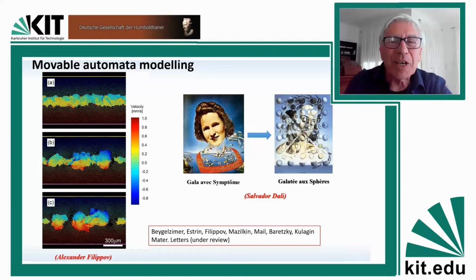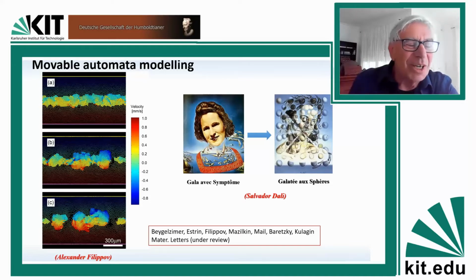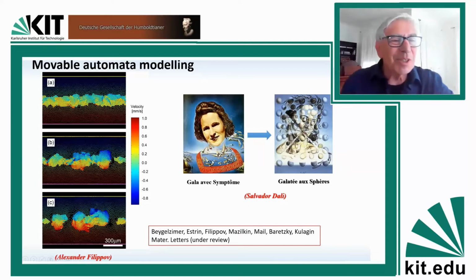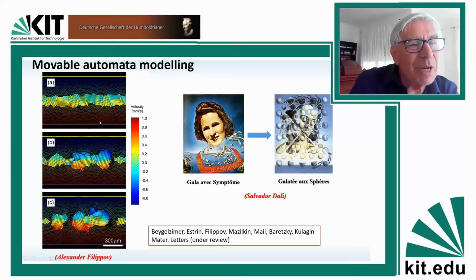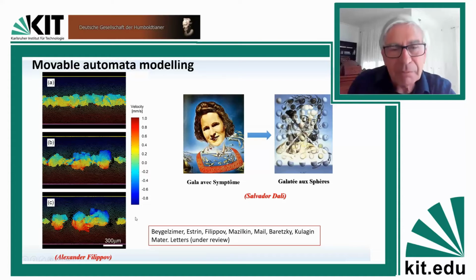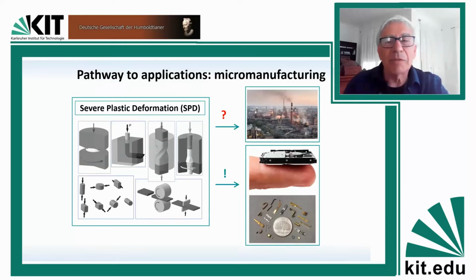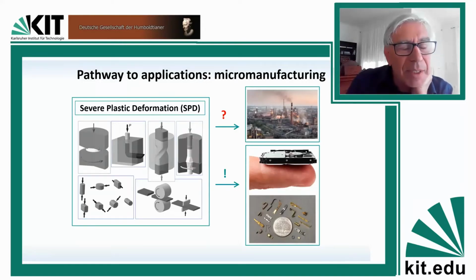Now, you introduce an interaction potential between these blocks or particles and look at how these particles flow. So you simulate the flow of a gas or liquid or a solid by looking at the movement of these particles. It's not molecular dynamic simulation, it's a much coarser scale, but this technique is quite powerful and it shows you how at different stages of the process you get this fragmentation of the hard layer. Now we have a tool with which we can try and predict what will happen in a multi-layered material when we deform it by one of the techniques that we propose.